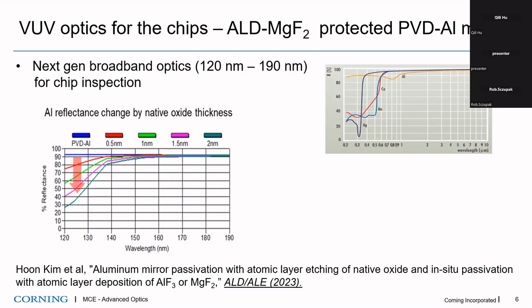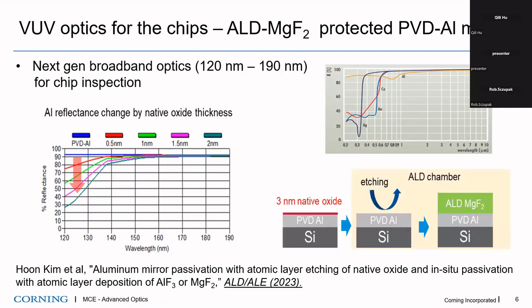So we have a program to try to find a solution. We are using atomic layer etching in situ to remove the 3 nanometer native oxide, and then using atomic layer deposition of fluoride to protect the aluminum mirror. That's still ongoing work, but our team at Sunnyvale presented some results last year at the atomic layer conferences.